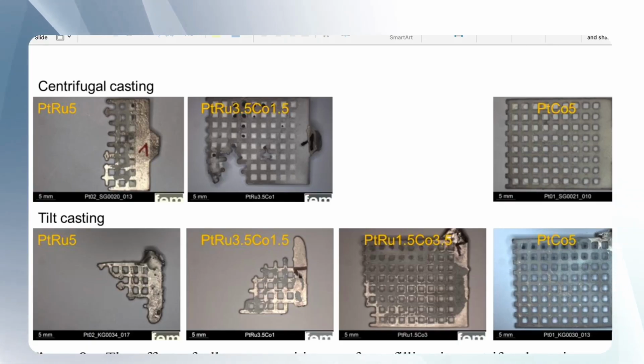Well, this figure shows centrifugal and tilt casting experiments. In the upper row we see the centrifugal casting, and in the lower row we see the tilt casting. We have a comparison here of platinum cobalt on the right and platinum ruthenium on the left. We cast this little grid, and with platinum cobalt we have perfect form filling for both centrifugal and tilt casting. If you look on the left side, the two images, you see that the form filling of platinum ruthenium is very low, especially in tilt casting. So platinum ruthenium definitely requires centrifugal casting because of its improved form filling capability.